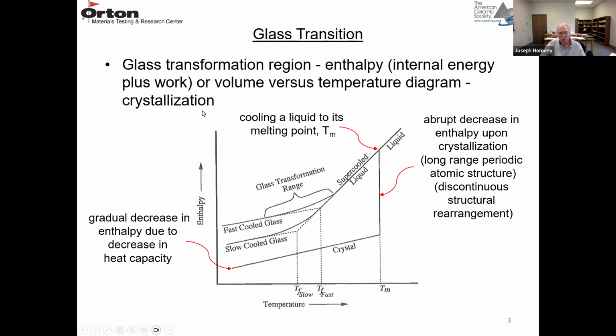So we'll look at what happens during crystallization. So it's this curve here. You have liquid, and then the crystal forms. So you start out with a liquid. You cool a liquid to its melting temperature, Tm. Tm is the melting temperature. And when the liquid crystallizes, you have an abrupt decrease in the enthalpy when crystallization occurs. So that's that large decrease. If it were volume, you'd also see a volume decrease. So now you have a long-range periodic atomic structure, and you have this discontinuous change when you crystallize. And then further decreasing the temperature, you have this gradual decrease in enthalpy because the heat capacity gradually decreases. If this were volume, you have a contraction as you decrease the temperature. So that's what happens when the liquid crystallizes.